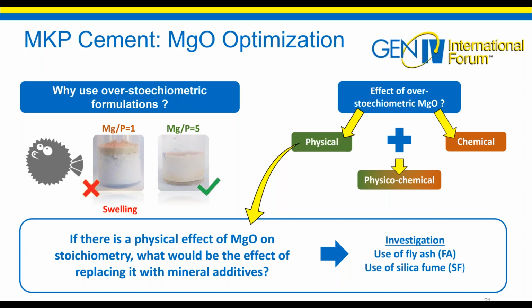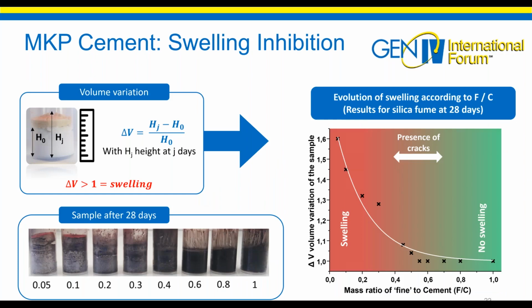It is one of the studies I have carried out. For this, I have used two types of mineral additive to substitute the magnesium oxide: fly ash and silica fume. First, I observe the effect of the amount of mineral additive on this stoichiometric matrix. I quantified the volume variation of the sample as a function of the mass ratio of fines to cement introduced.